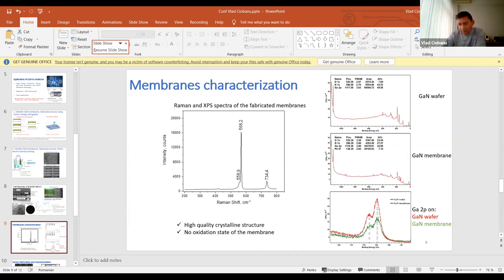Now, looking at the gallium nitride membrane, we also found around 7% of silver, which corresponds to contamination from the silver paste we used during the photoelectrochemical etching step, where we use it to contact the surface of the material to the electrode.